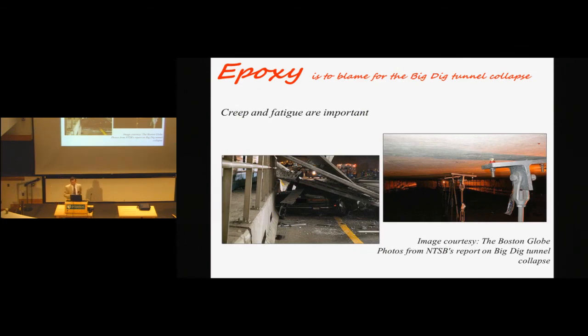The famous accident in Boston, the collapse of the roof of the tunnel, has been actually assigned and eventually traced to failure of an epoxy adhesive. So what you see over here are these failed anchors to the roof of the tunnel. That led to, of course, some material damage, but also to loss of life. So why did it fail? It failed because of fatigue and primarily because of creep.